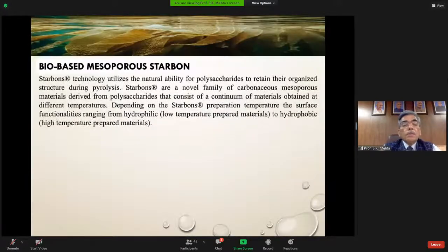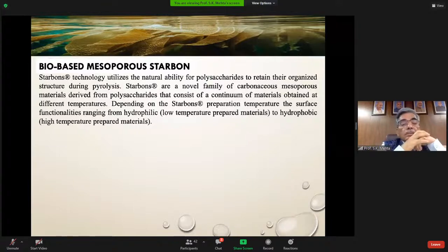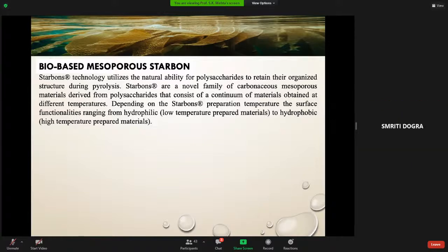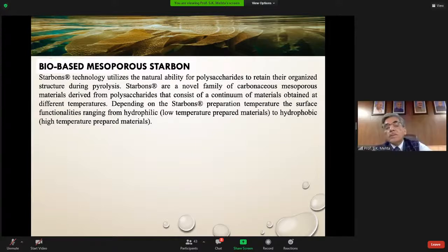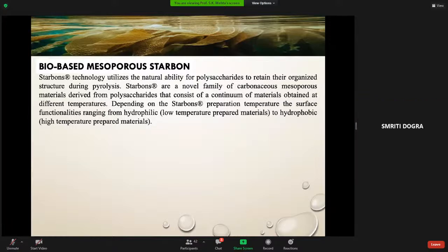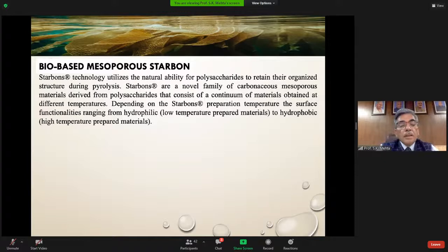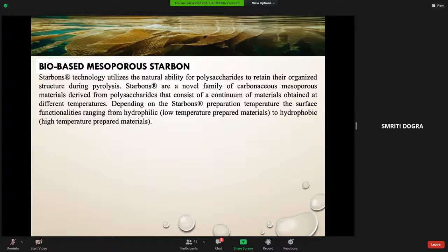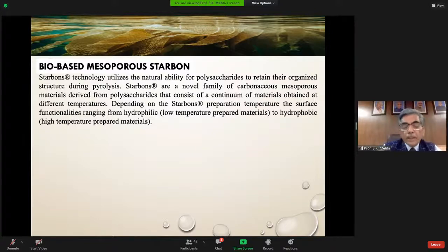Now, the bio-based mesoporous Starbon technology utilizes the natural ability of polysaccharides to retain their organized structure during pyrolysis. And Starbons are a novel family of carbonaceous mesoporous materials derived from polysaccharides that consist of a continuum of materials obtained at different temperatures. Depending on the Starbon preparation temperature, the surface functionality, ranging from hydrophilic, that is low temperature prepared materials, to hydrophobic, that is high temperature prepared materials, can be produced.